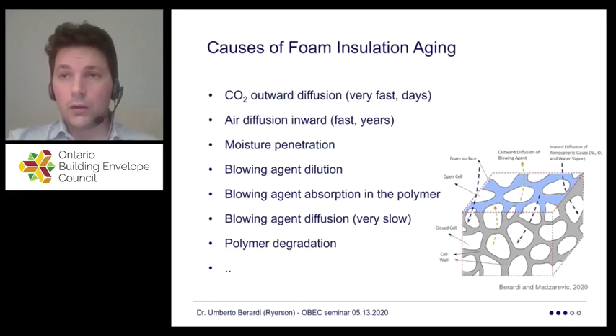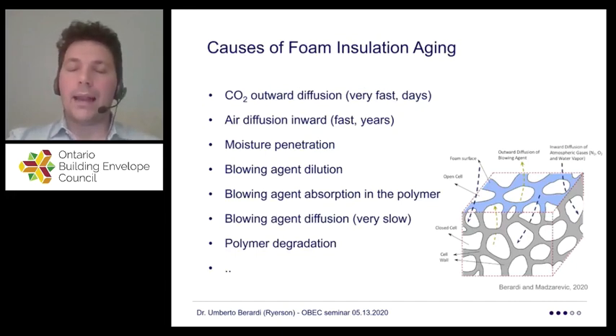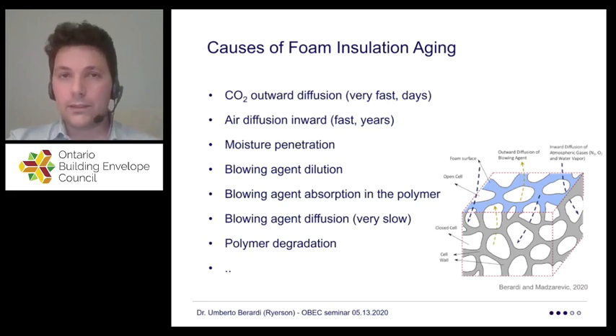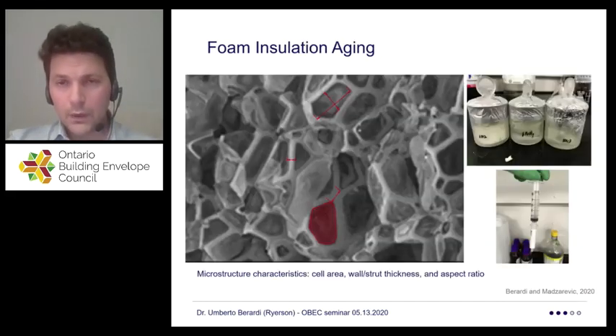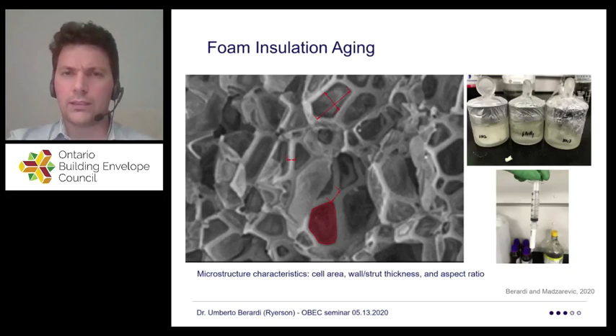This kind of aging occurs because the gas escapes, moisture enters, it gets trapped, and it changes the gas balance within the porosity of any insulating product. Once you get moisture content into the material, then the moisture stays there for quite a significant amount of time. And we've been doing a lot of work also trying to understand how long it takes for moisture to escape, how long it takes for a blowing agent to escape from a foam, and how we can get a sense of what is going to be the long-term behavior of these products 10, 15, 20 years from now.